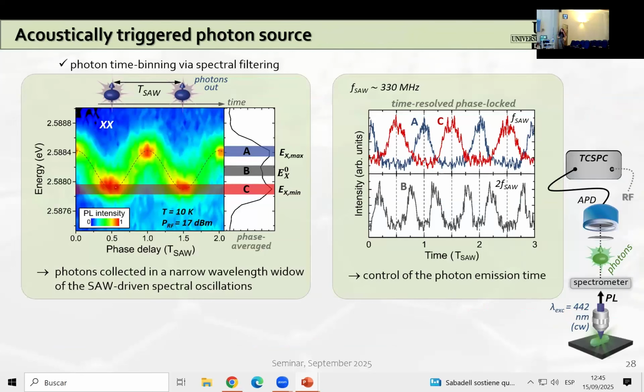In addition, we can now use this ability of the acoustic wave to induce such fine spectral tuning of the quantum dot transition energies. And we can basically combine it with spectral filtering in order to control the photon emission time. This can be done simply by collecting the photons in a narrow wavelength range here.